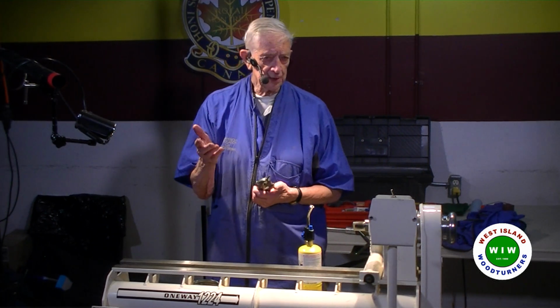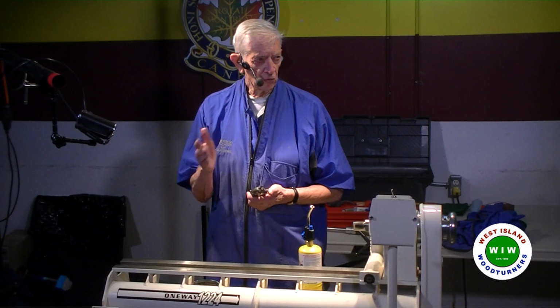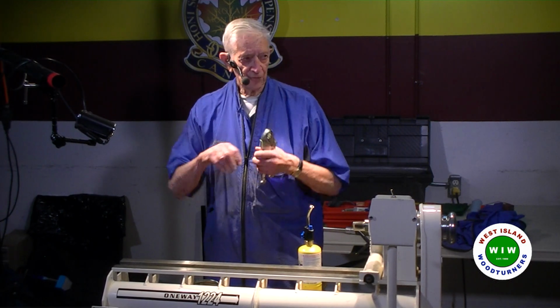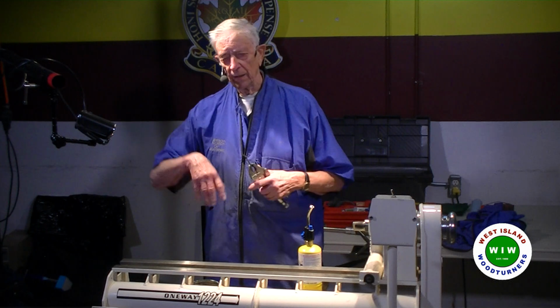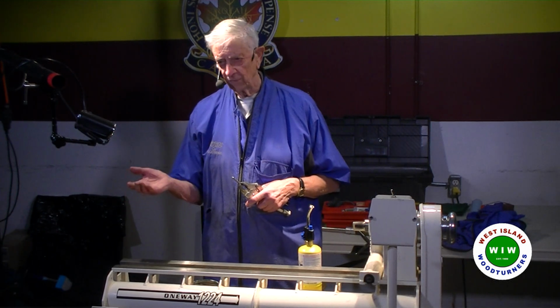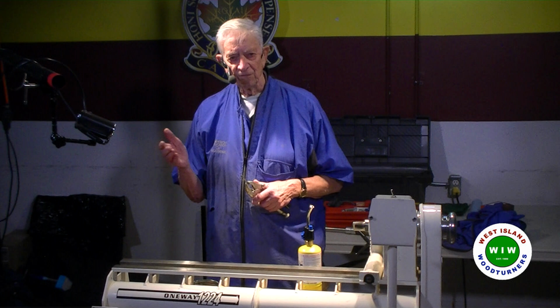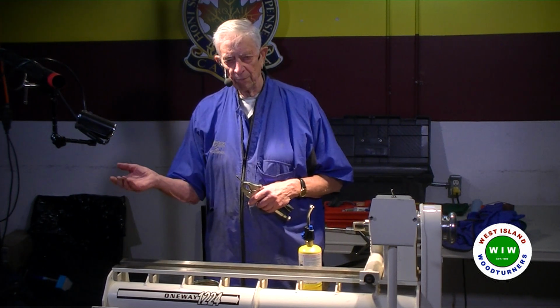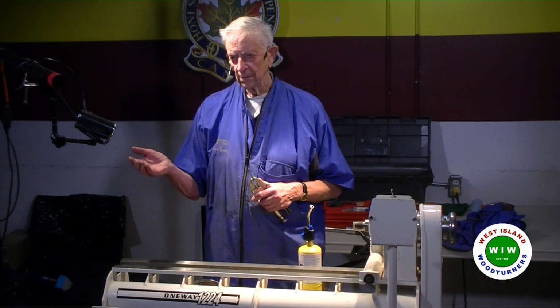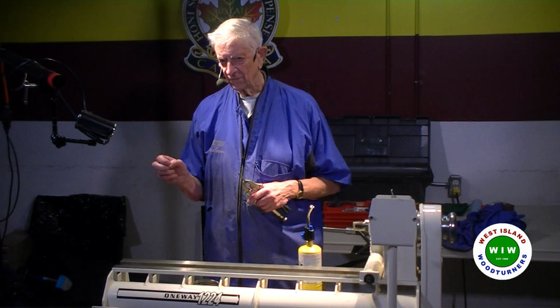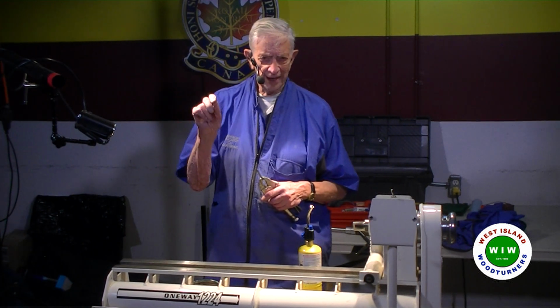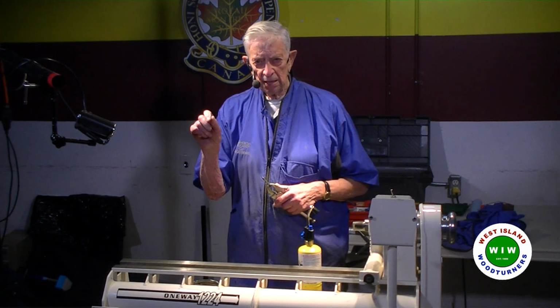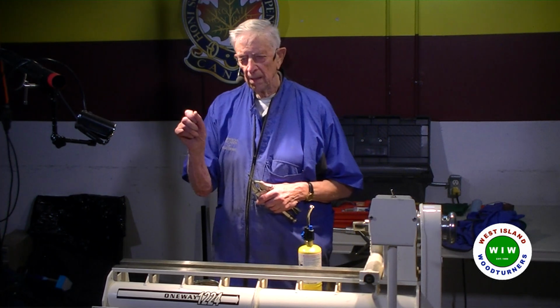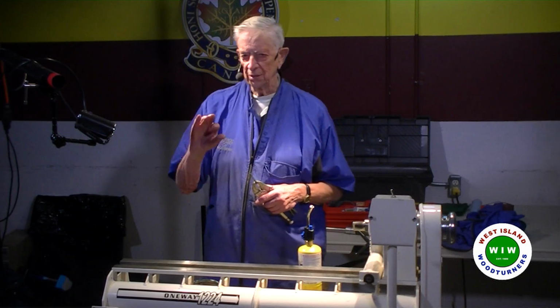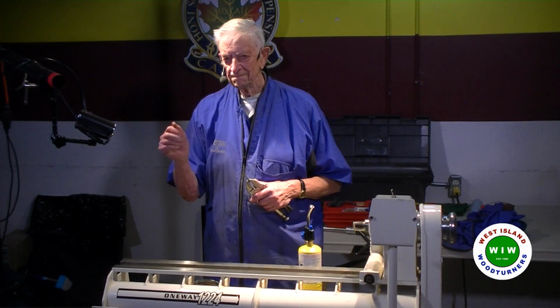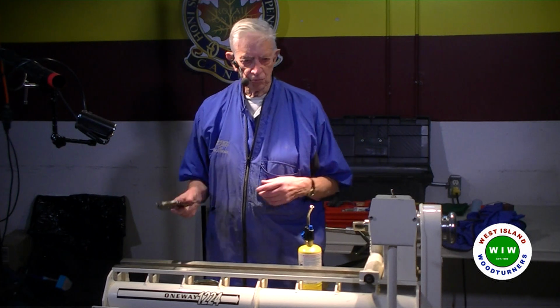Like crowbar steel, you can only get to about 50 Rockwell, the maximum, but you have the tensile strength in it. If you want to have a steel for cutting, you've got to be at least 58, 60. You can go higher on that scale, up to probably 65, but the fine edge at 65 and plus is so brittle that it can chip. So the best range is between 60 to 63, and that's what we try to achieve.